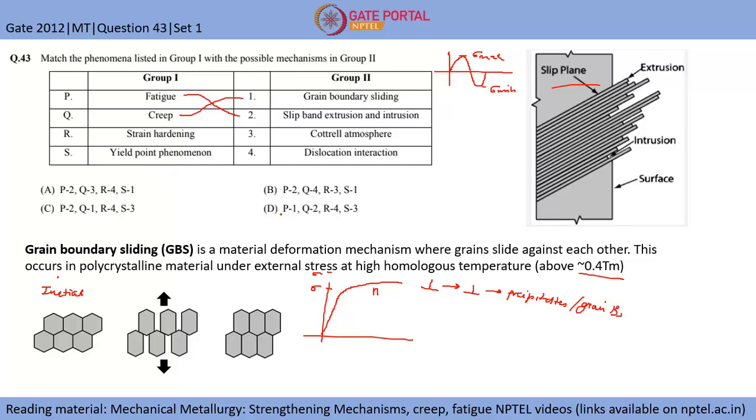So the dislocations interact with each other and form sessile locks. Let's say two dislocations interact and are locked in certain positions, such as jogs or kinks. This will impede the motion of another dislocation moving on the same plane, which will harden the material more. Hence strain hardening is basically because of moving dislocations, and these moving dislocations interact with each other to form sessile locks, which directly or indirectly harden the material. So R is 4.